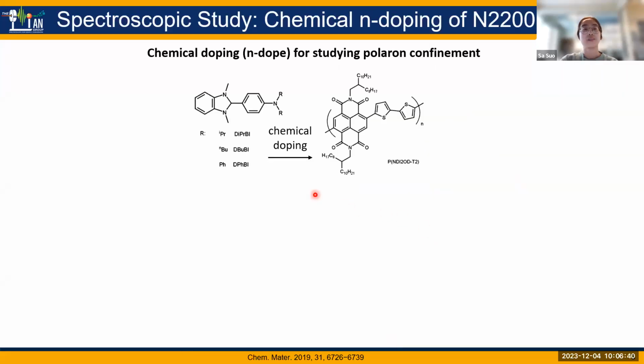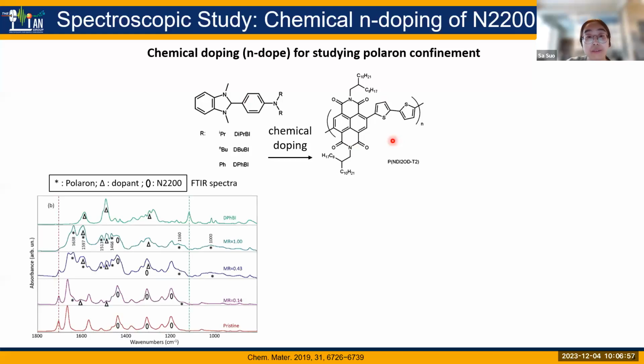So here I'm gonna show a case of spectroscopic study under chemical doping, N-doping of N2200. They used differently substituted benzimidazole dopants to dope the N2200, and they used FTIR and also Raman, which I will show later, to study the doping effect. So here shows stacked FTIR spectra. On the top is the spectrum for the dopant itself, and the bottom is the spectrum for pristine N2200 itself. And MR over here stands for the molar ratio between dopant and N2200. So we can look at the MR equals 1, which has the largest doping effect.